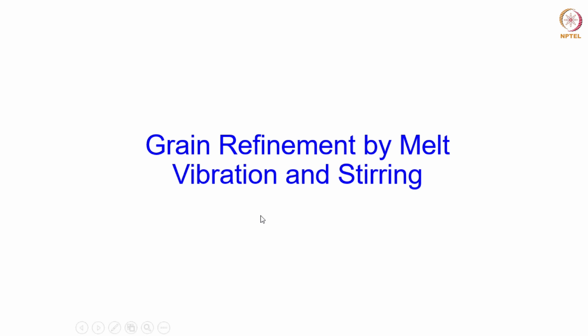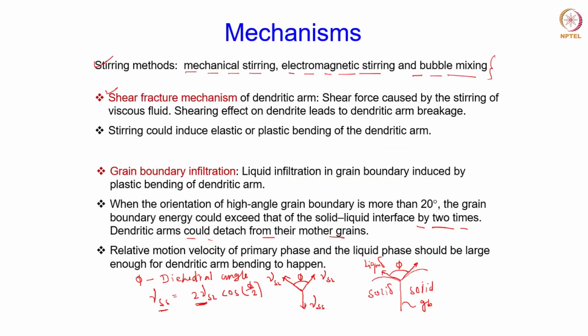So if you recall, we discussed grain refinement by melt vibration and stirring. This is one of the ways of grain refinement during solidification, apart from the melt inoculation that we talked about before. Here the melt is physically stirred by some means such as mechanical stirring or electromagnetic stirring, and at times you can also apply ultrasonication. Once you create that agitation in the molten metal, the force which the molten metal is subjected to will lead to phenomena giving rise to grain refinement. The mechanisms through which that occurs are what we discussed in the previous class.